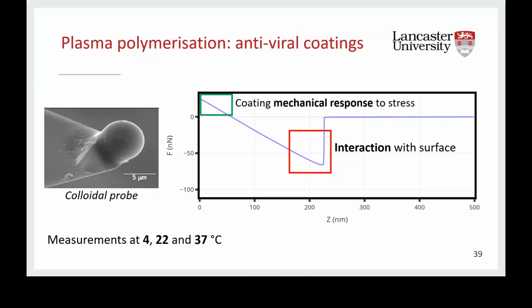However, around 230 nanometers, you can see that the force becomes negative, meaning that actually the tip is attracted to the surface. Then, as we try to move the tip closer to the surface, the force increases until it crosses the 0 line. At this point, the tip is actually touching the coating, and we are squeezing the coating. And from this part of the first curve, we can measure the mechanical response of the coating to the stress applied by the tip.